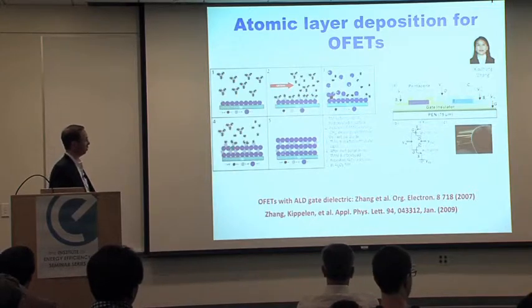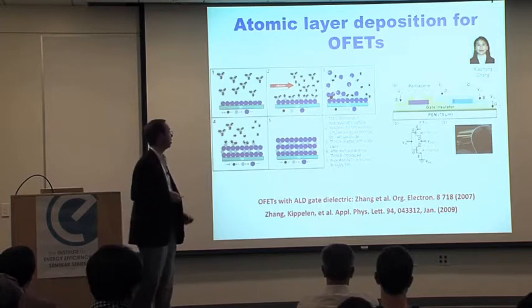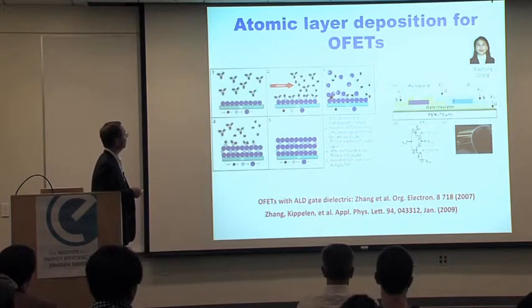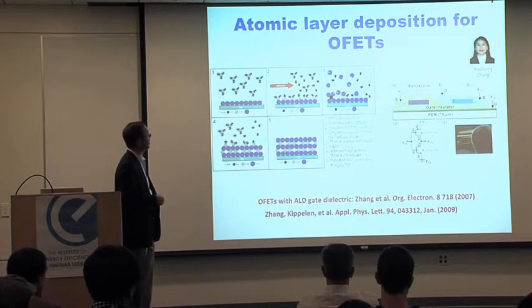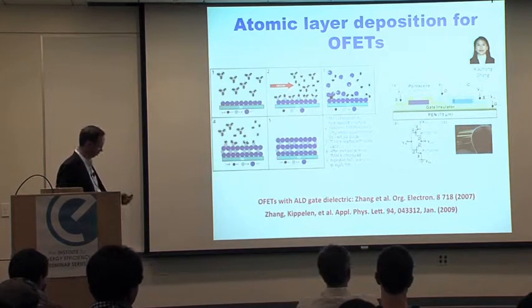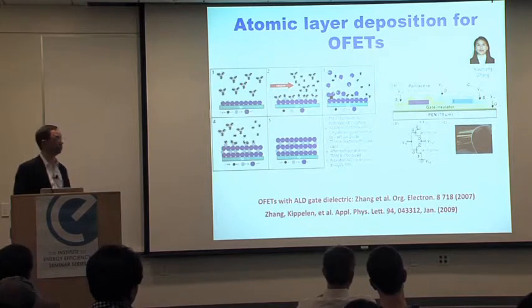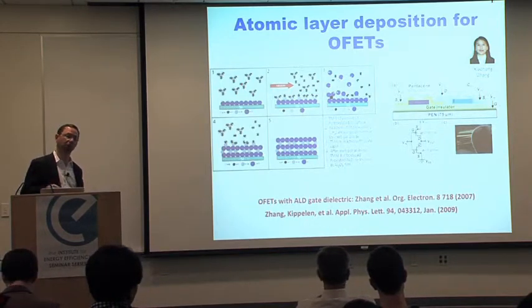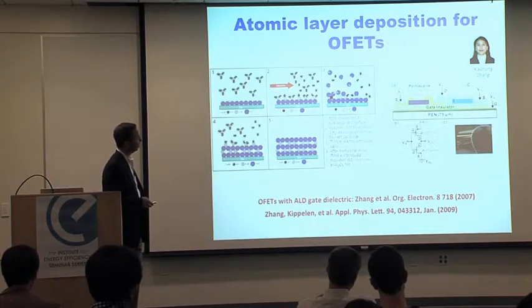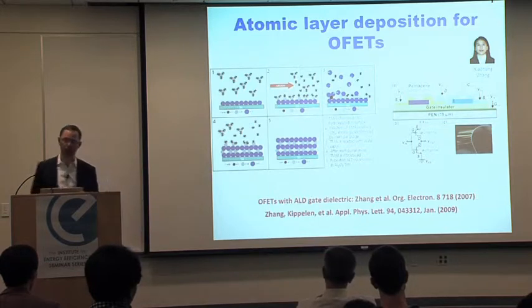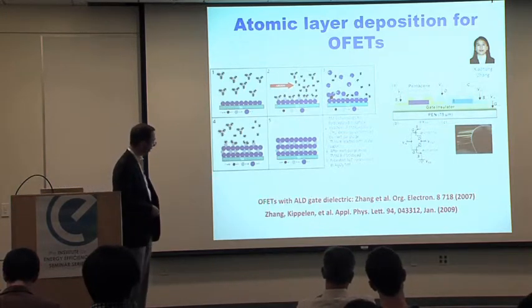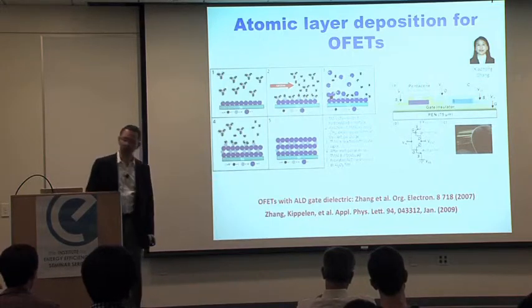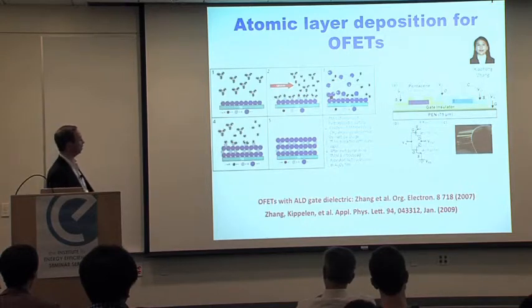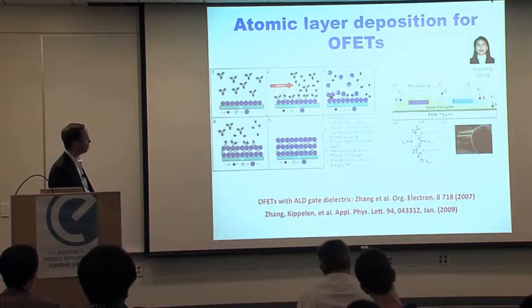In this particular case, it's just a cartoon showing how you can grow aluminum oxide films, where you have water and trimethyl aluminum, and by alternating these precursors and purging the chamber in between, you can grow layer by layer very high quality dielectric layers, with a fairly high dielectric constant also, which is quite interesting because you want the high dielectric constant to increase the capacitance density of your gate insulator to decrease the operating voltage of your transistor. The use of ALD in organic field effect transistors is something we pioneered back in 2006, 2007, and we've demonstrated complementary circuits with materials like pentacene and C60.